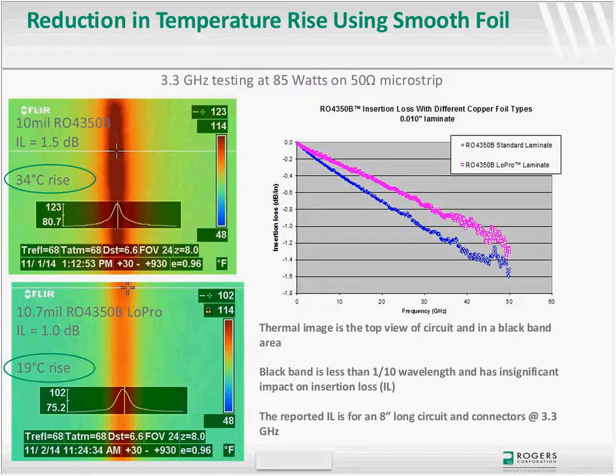The added benefit we found, and here we have an example where we measured one of the thermoset materials from Rogers, the RO4350. We were looking at the version with a low-profile electrodeposited copper that is trademarked low profile, and then the traditional electrodeposited copper that typically comes with this material. You can see, at least on the graph, the difference in the insertion loss when one measures the microstrip 50 ohm insertion loss for this 10 mil material. You can see the improvement in insertion loss at 30, 40, 50 gigahertz, where some of these applications may be. But the added benefit we found in doing some thermal imaging is that the reduction in RF heating can be significant as frequencies go higher.